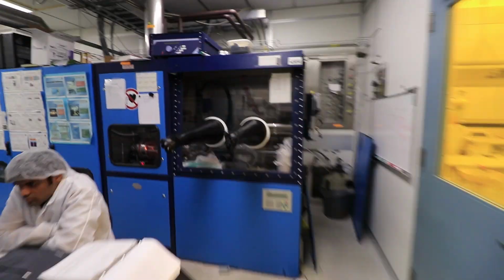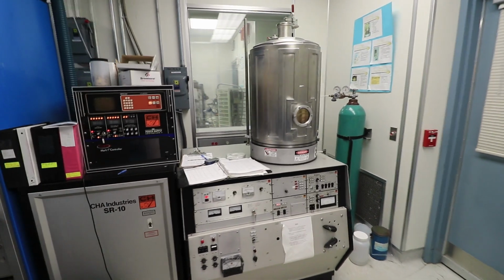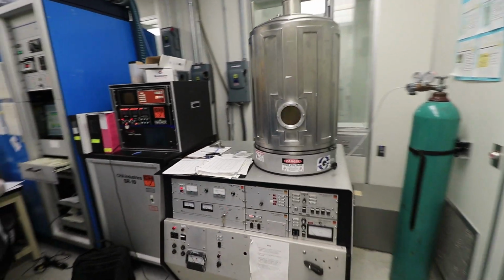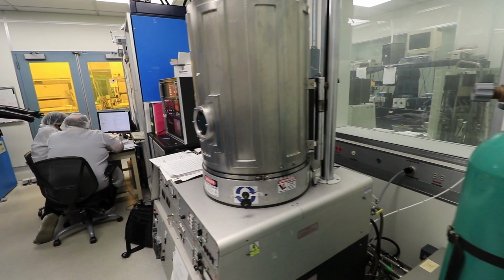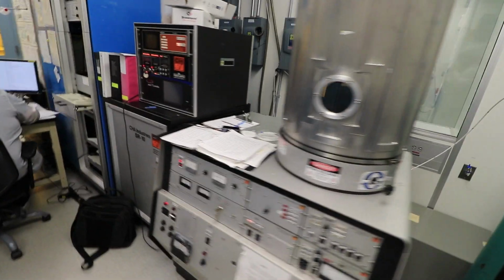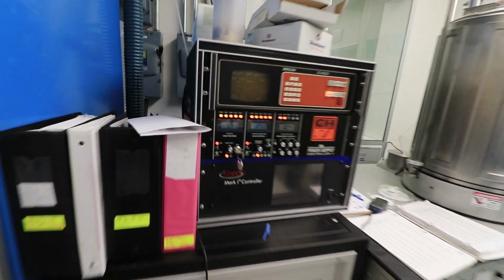An electron beam evaporator is used to deposit various metals onto semiconductor films for the realization of ohmic and Schottky metal contacts. This system incorporates a four-pocket crucible as well as a secondary thermal evaporation source that can be used to deposit gold germanium. It is also equipped with a Veeco Mark I in situ argon plasma cleaning system that's available to prepare the surface prior to metallization.